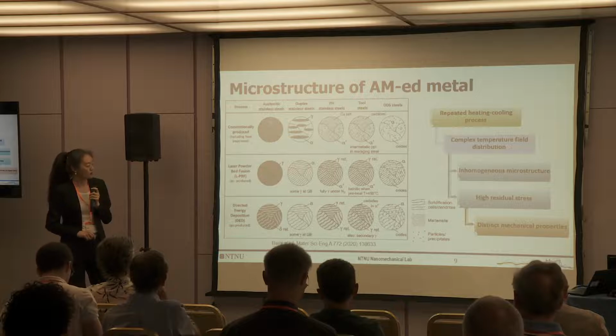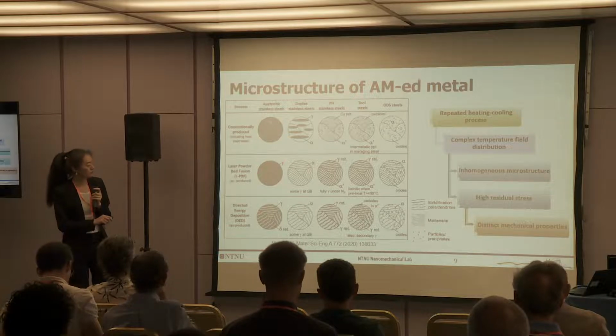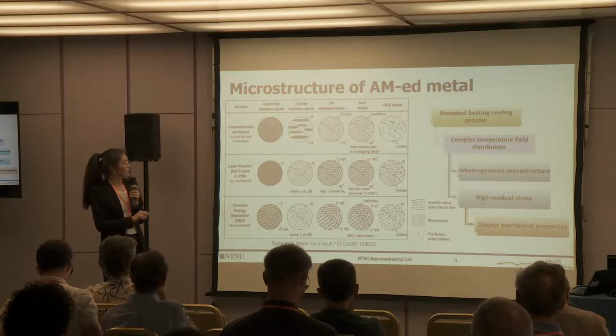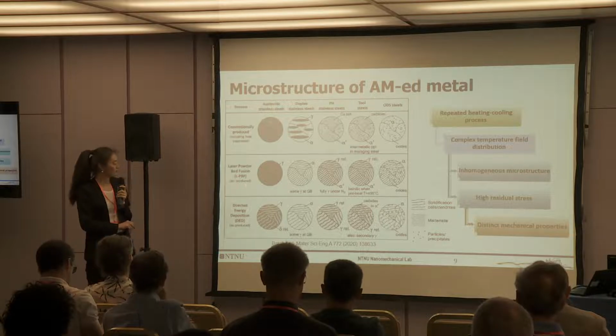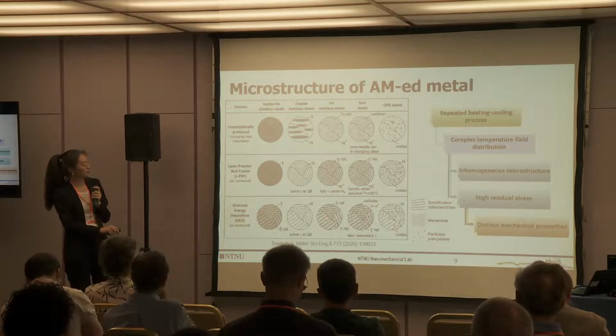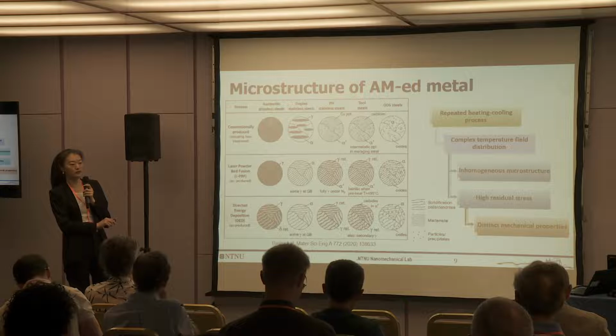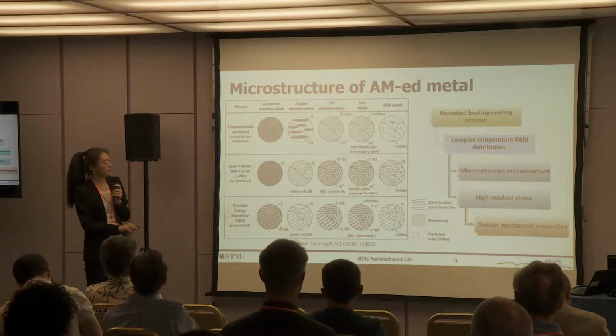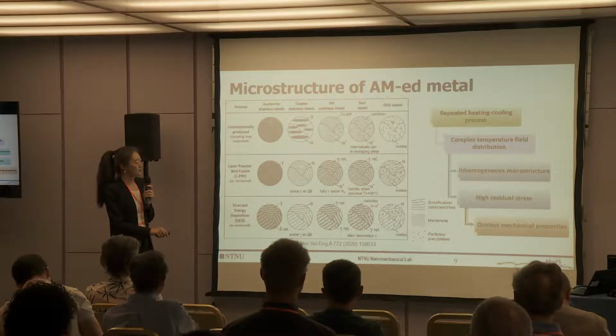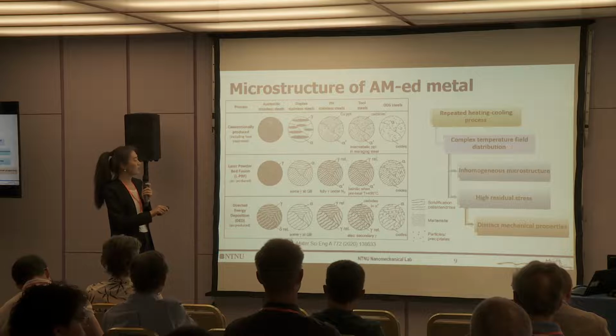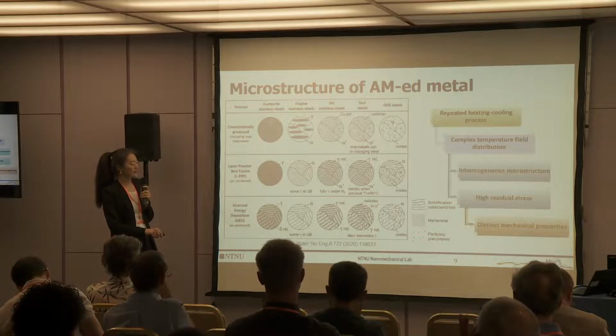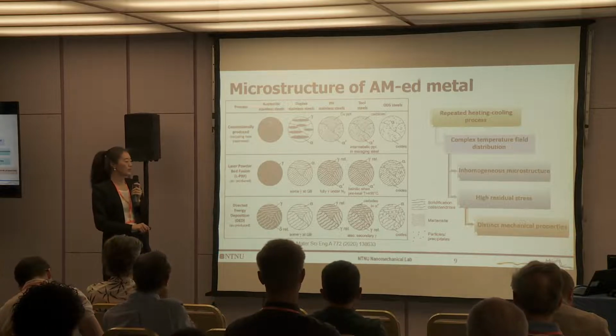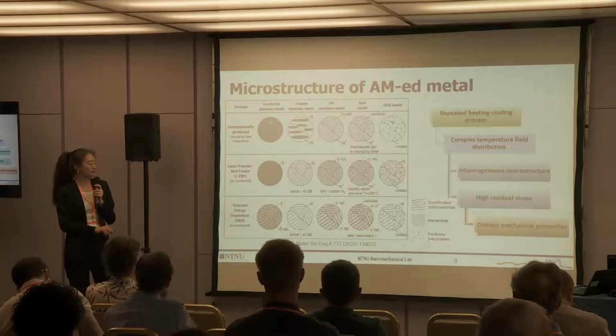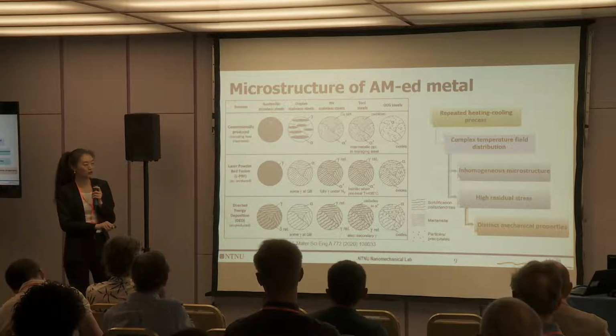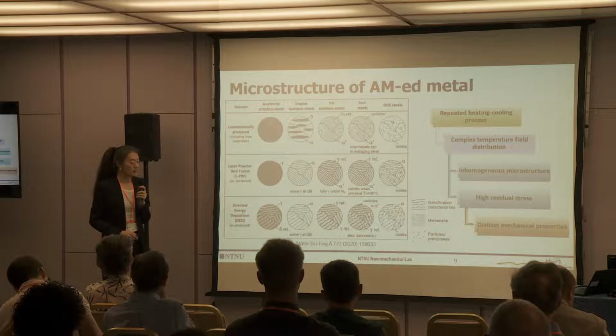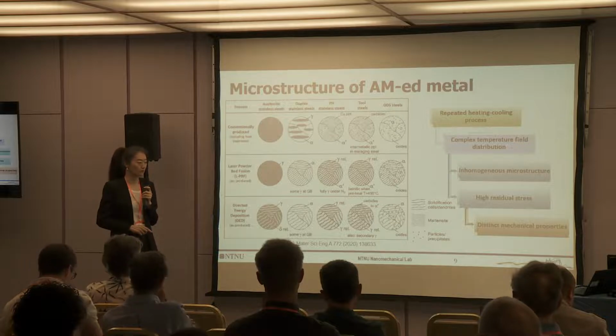I borrow a figure from Professor Dirk Rep here to compare additively manufactured steel microstructure with conventionally produced steel. And we can see that no matter whether it is the solidification cells, the martensite, or the precipitate size and distribution, AM provides a very different microstructure. And this, of course, makes the mechanical properties very interesting.